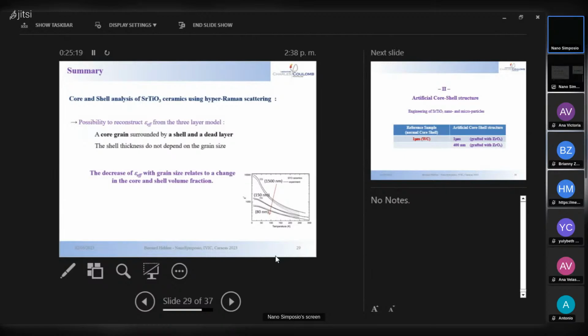Okay, to summarize on this part, it is possible using hyper-Raman scattering to reconstruct the effective dielectric constant of the grains in a tight way by using the layer model, a core grain surrounded by a shell and a dead layer. The shell thickness does not depend on the grain size. That's what we found also.